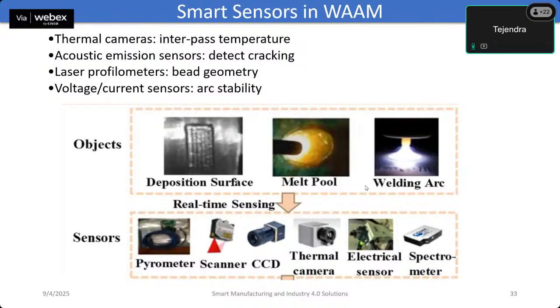As we discussed in the previous slide, different sensors can be used. These sensors are the most important elements because they act as the eyes and ears of the system. For example, thermal cameras can be used to measure the interpass temperature. This ensures that the next layer is deposited under the right thermal conditions, avoiding excess heat accumulation that could result in poor bonding or delamination.